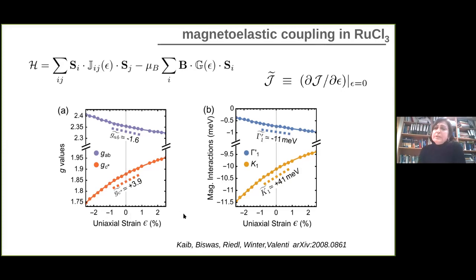And what I would point out, what we observe that is very interesting, is that when you look at the changes in your parameters as a function of this uniaxial strain, this gamma prime interaction, basically this slope, becomes extremely important. So it's telling us that this term is going to play an important role in these effects of straining the system. The same happens also with the Kitaev.